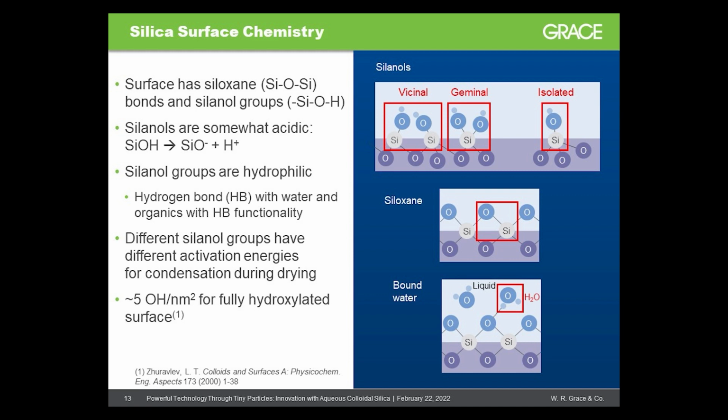Adjacent silanol groups can also undergo a reaction that produces water as a byproduct, with the result being additional siloxane bonds. This type of water is referred to as chemically bonded water. It is more difficult to remove than physically bonded water, and so this condensation reaction occurs at higher temperatures than removal of the physically bonded water. This silanol condensation reaction is a key functionality in binder applications.